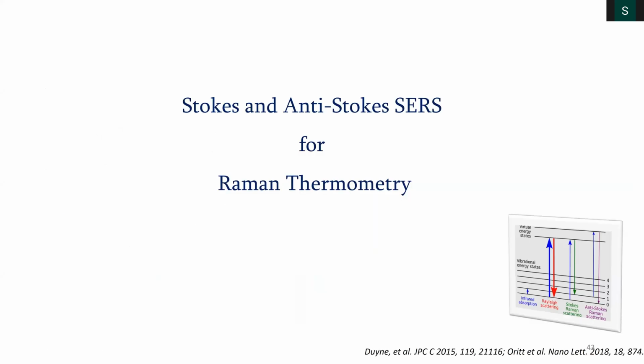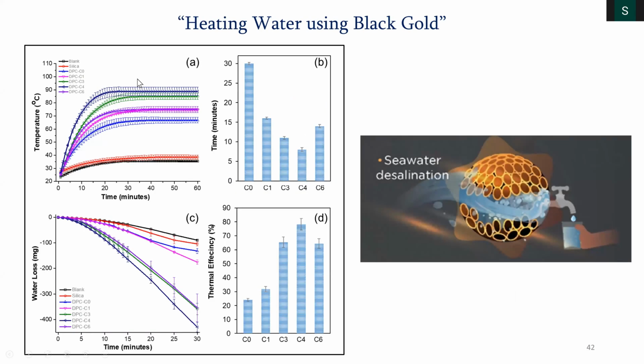We also wanted to know the temperature of the surface. See, this says it can heat up to 90 degrees Celsius, but this is not the temperature of the gold surface, because once the heat goes from gold to water, water cannot boil above 100 degrees Celsius. That's one question. But then there is a heat loss from water to the environment, right? So this is not the way to see the surface.